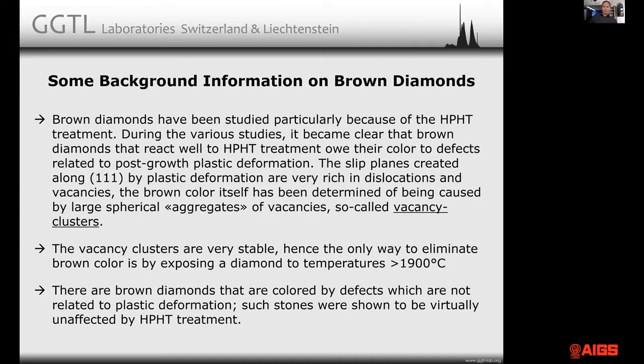Now, these vacancy clusters are far more stable than a simple vacancy. Simple vacancies start to diffuse and anneal out from about 500 degrees upwards, 600, 700, 800, 900 degrees. The simple vacancy disappears in a diamond. A vacancy cluster is very stable. And the only way to eliminate a vacancy cluster is by exposing a diamond to a temperature from about 1,900 degrees up. And this is done by HPHT treatment.